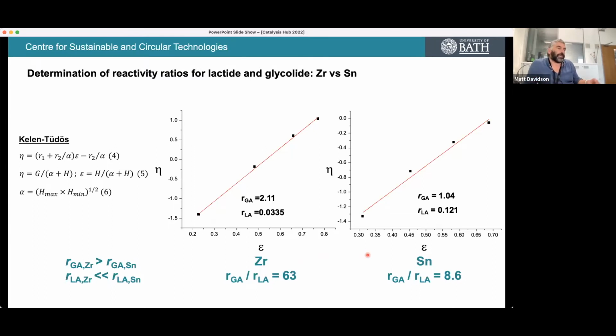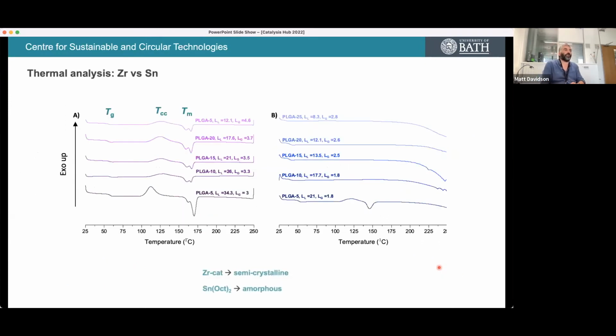We can establish the reasons for that by doing some kinetics, and Neve's done a lot of these kinetics that lead to the reactivity ratios of glycolide and lactide for comparing the zirconium and the classical tin catalyst. To cut a long story short, and there's an awful lot of data contained in this slide, so it doesn't really do it justice: if you compare the zirconium to the tin, the reactivity of glycolide ring opening in the zirconium case is greater than that of the tin, but the reactivity to lactide is significantly less than that for the tin. So the reactivity ratio for zirconium, the proclivity to ring open glycolide rather than lactide, is significantly greater than the reactivity ratio for glycolide over lactide for tin. And that's what gives us this significantly more blocky structure. Remember, we can do this in the melt, and it's a one-pot reaction where we throw all the monomers in at the same time. So this is at least potentially amenable to an industrial process, or at least scaling up.